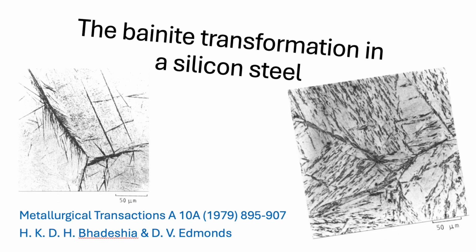Did carbides eventually form? Yes. They heated the UB structure, with its ferrite and high carbon austenite, to around 500 degrees C. And the retained austenite finally decomposed. Carbides nucleated, interestingly, right at the interface between the austenite and the ferrite, and then grew into the austenite, consuming the high carbon austenite. Right, and initially it wasn't even cementite. It was a temporary transition carbide, a specific iron-silicon-manganese carbide, reflecting the alloy elements trapped in the austenite.